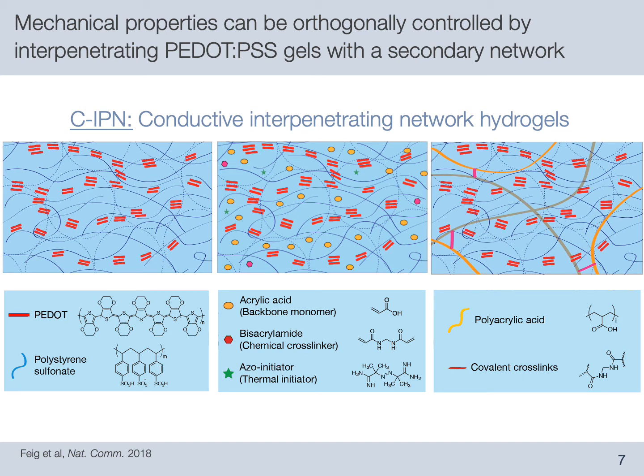As a proof of concept, we backfilled PEDOT:PSS hydrogels with acrylic acid monomers and a thermal initiator, which was needed because UV light does not effectively penetrate the opaque PEDOT:PSS gels. After initiation, the acrylic acid polymerizes into polyacrylic acid, resulting in conductive interpenetrating network hydrogels, or what we call CIPN.